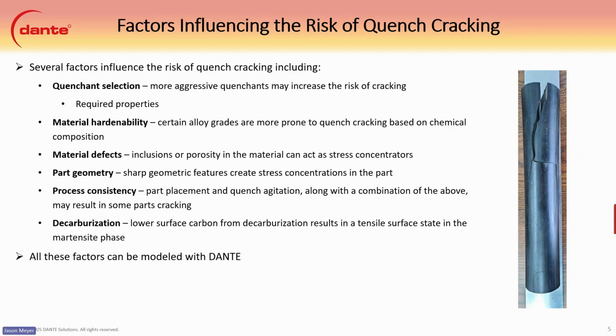So, the factors influencing quench cracking. Several factors that influence it are, first, quenchant selection. A more aggressive quenchant may increase the risk of cracking, but you also have to bear in mind that you need to keep your mechanical properties if you go to a slower quench. Second, material hardenability: certain alloy grades are more prone to quench cracking based on chemical composition. Third, material defects can have a big effect on stress concentrations, including porosity in the material. When they go through heat treatment, those porosities can cause really high stress concentrations, causing cracks. Part geometry, like sharp geometric features, can cause stress concentrations from thermal strains. Process consistency, like part placement in the quench agitation, along with a combination of the above, may result in some cracks.